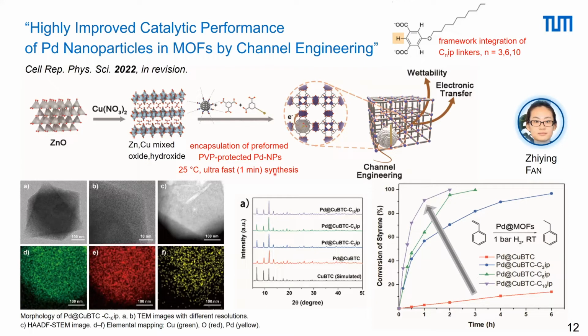smooth synthesis condition. Then, she integrated a special kind of defect-generating linker by a mixed linker approach into the MOF network. So we have this isophthalic acid linker with this long chain here. And these long chains point into the cavities. So what you do, you change the hydrophilicity of the MOF material, of the host, and this has a drastic effect on the catalytic performance.